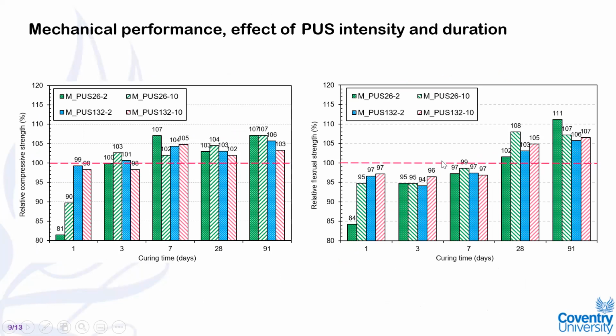and on the right the flexural strength due to the various sonication frequency and duration. As you can see, at a very early age, 1 day, the sonication has decreased both the compressive strength and flexural strength. This could be related to the disruption of ettringite formation, retarding hydration at a very early age upon application of sonication. We discussed this in our previous study on pore solution.